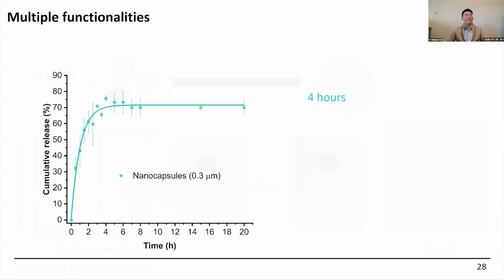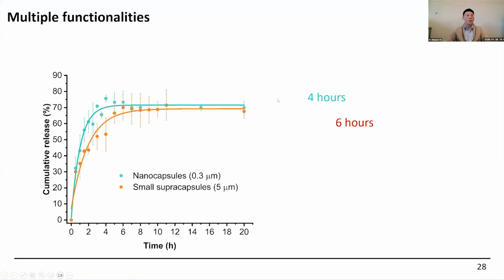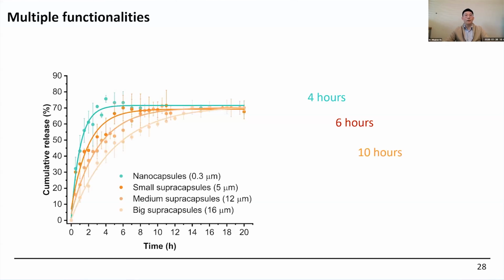Okay, and furthermore, because we want to use it for biomedical applications, we want to see the cargo release profile of our supracapsules. We know the simple nanocapsules can release dye or cargoes through diffusion through the polymer shell. And in our case, the nanocapsules reach the plateau of the release after 4 hours. And once we compare with our supracapsule, we can see the plateau time is extended. And with this, we know we can have sustained release from our supracapsule systems.